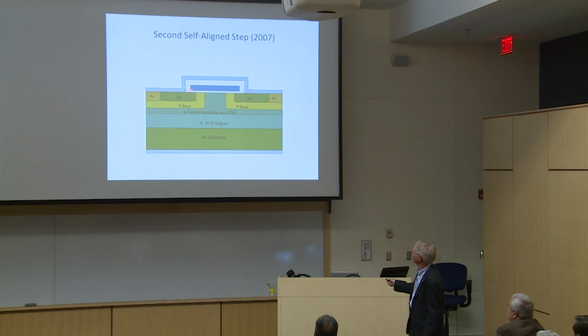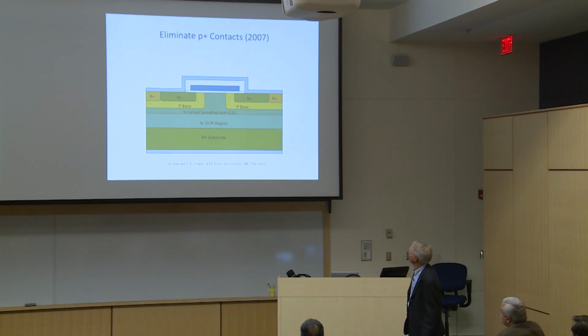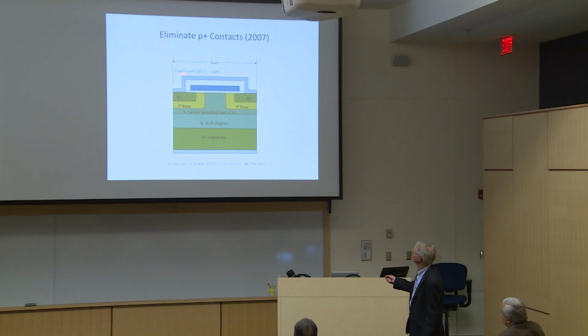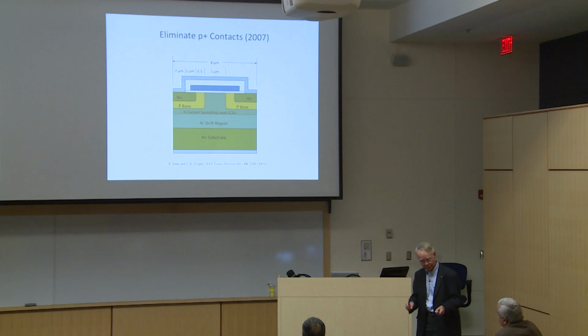And we've reduced, or eliminated, the alignment tolerance here, and this is now maybe a half micron. So we've shrunk a lot of things. Finally, the last thing we did was we decided to remove these P+ contacts. And if you take them away, in 2007, we were getting cell pitches of about 8 microns or so with this full-up process. Now, you do have to make contact to the P base. It doesn't carry current, but you have to nail down the potential.